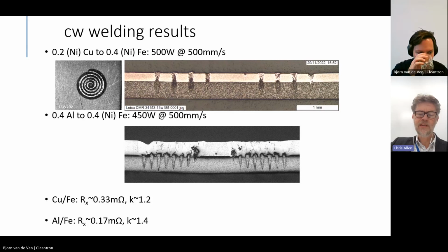So the way that these 2 laser beams from these 2 different lasers interact with a variety of different materials that you might be interested in terms of bus bars and cell terminals, for example, so often forming an overlapping stack of 2 different materials. The way in which these laser beams will interact with those stacks depends on the material, of course, and also the characteristics of the laser beam. In this example, this is just showing you some scanned spiral-shaped welds that we've developed for joining together nickel-plated copper bus bars onto steel terminals of cells, cylindrical cells in this example, and a similar approach with the slight change in parameters for joining aluminium bus bars to steel cells.